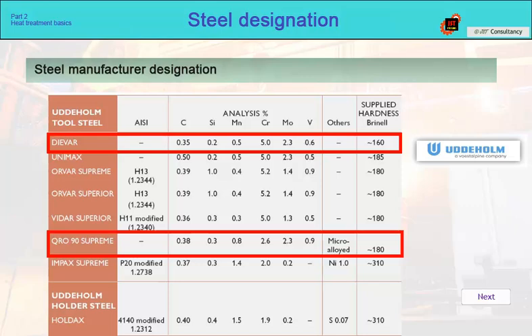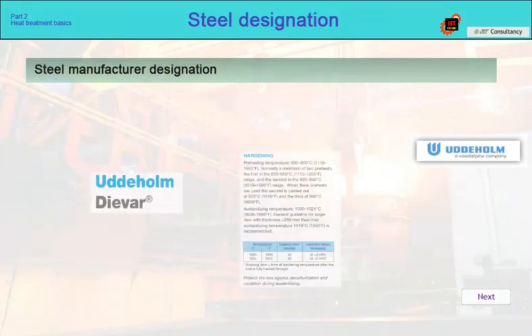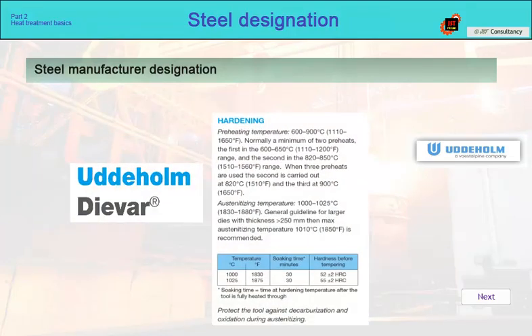In the case of their heat treatment, it is therefore necessary to proceed strictly according to the recommendations of the steel manufacturer, and not according to general standards, both international and national. This is very important, because in some cases, these steels with trade names do not have an equivalent in EN. A striking example is Dievar steel, which is currently used for high-pressure die casting dies. If this steel grade is indicated on the drawing, the heat treater is obliged to proceed according to the Uddeholm regulations for this steel grade.